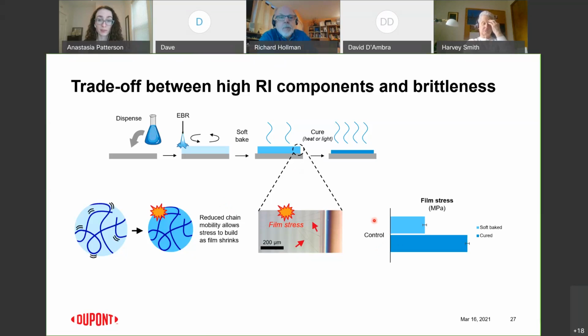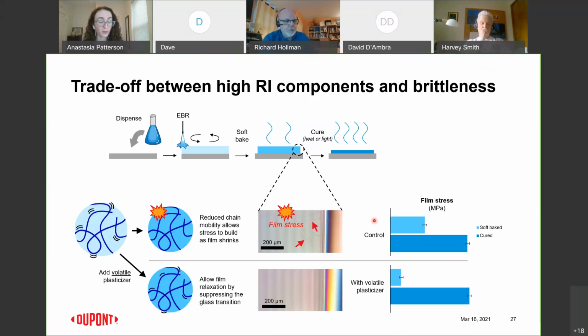So a lot of times, if you're thinking about polymer physics and glass transitions and things like that, plasticizers come to mind. If you're trying to reduce stress and let the film relax, you can add a plasticizing element. But you might guess that I'm going to say that plasticizers tend to be lower refractive index. And so that was not a great option for us in terms of something that would stay in the film. So instead, we took the approach of adding a volatile plasticizer, so something with low molecular weight that could evaporate at the end of the whole process.